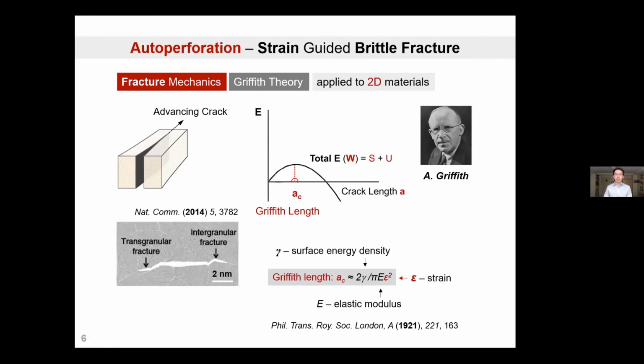Here's a piece of graphene under TEM. As we all know, CVD grown, or chemical vapor deposited, graphene or other two-dimensional materials always have these inherent grain boundaries or defects on the order of nanometer scale. These defects can be seen here. If we think about these defects as seed cracks that exist within our material, I'll actually say that the seed crack you see right now is shorter than the Griffith length, with the reason being that it is stable enough for us to take this TEM image, right? So this seed crack has to be on the left-hand side of the Griffith length.